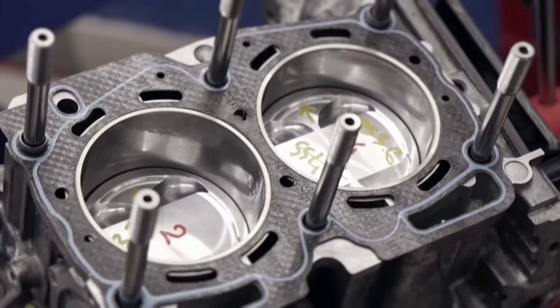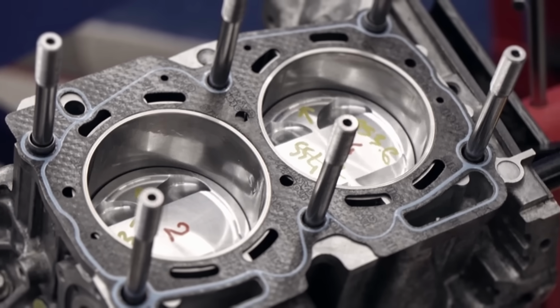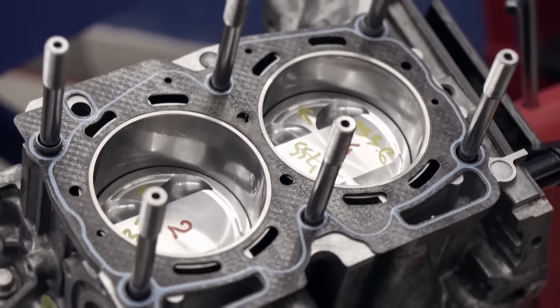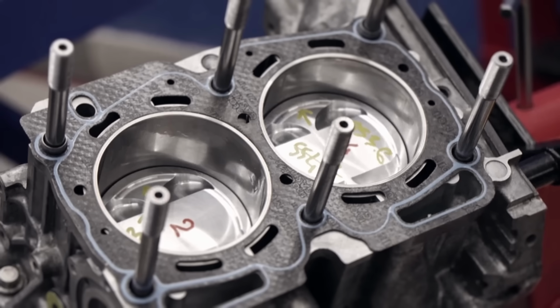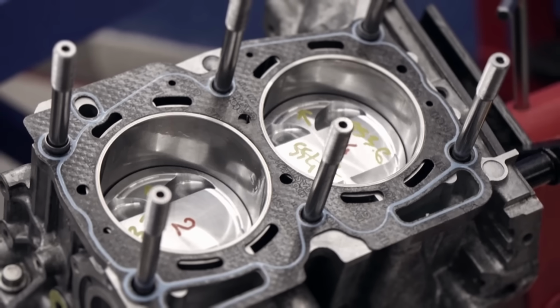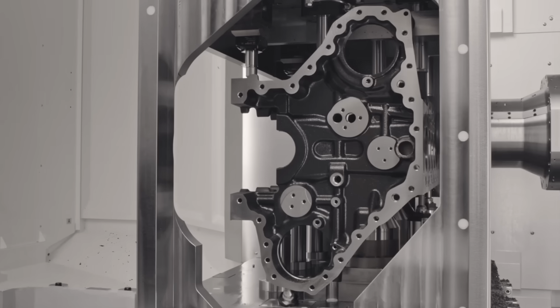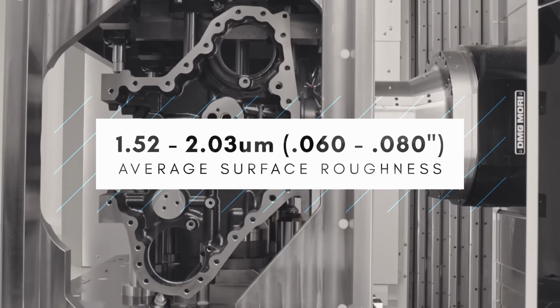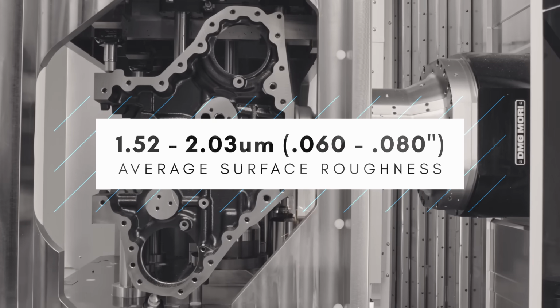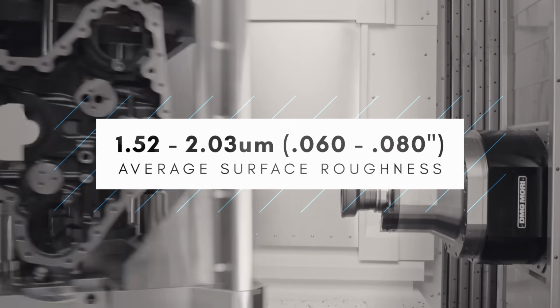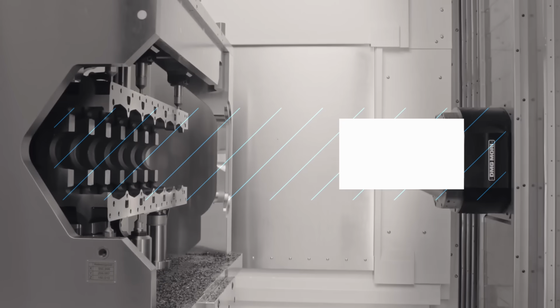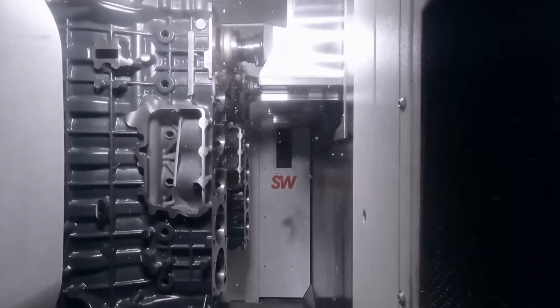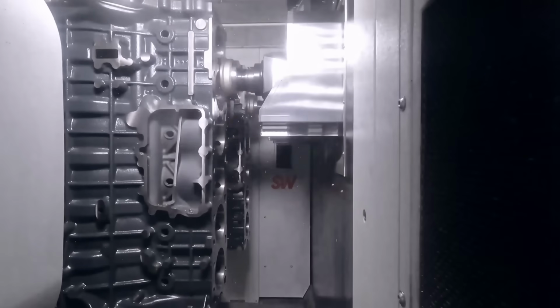While composite gaskets can form easily, are compressible, and have excellent mechanical strength, the nature of the beater-add coating makes them highly susceptible to the mating surface quality, cleanliness, and overheating. They generally require highly paralleled block and head faces with an average surface roughness of about 1.52 to 2.03 microns. This is roughly equivalent to a sandpaper grit finish between 120 and 160. Rougher surfaces limit gasket conformance, while smoother surfaces increase the tendency for the gasket to flow and reduce its blowout resistance.